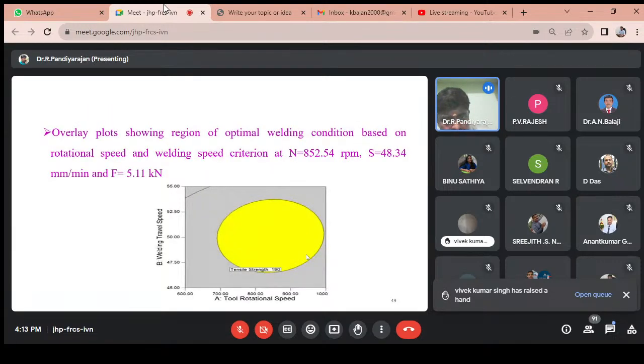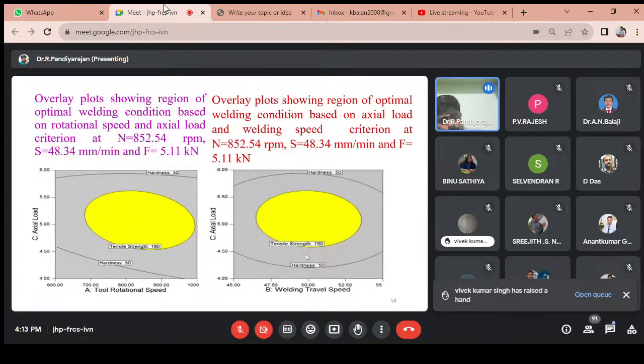Once we set the input parameters for the desirability approach, we plot the overlay plot. The overlay plot shows the optimum process parameters of the friction stir welding process.